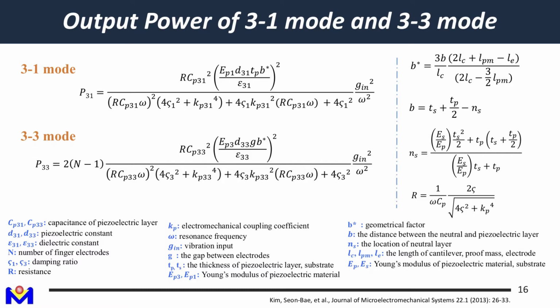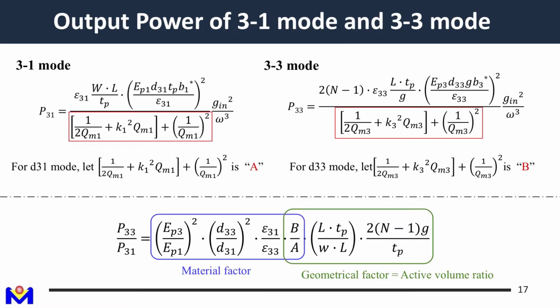But what we are concerned about is actually the normalization here. For example, P33 versus P31, the ratio depends on which kind of parameters. So after certain kind of simplification, we can get a very simple relationship here. For P33, the power generated from 3-3 mode over power generated from 3-1 mode. The blue rectangle actually depends on the material, so we call it a material factor. And the green rectangle is mostly geometry. So we call it a geometry factor.